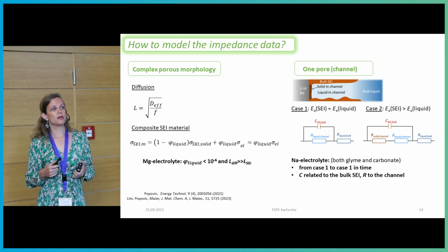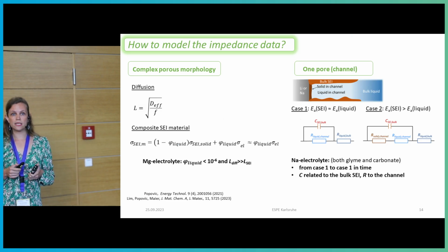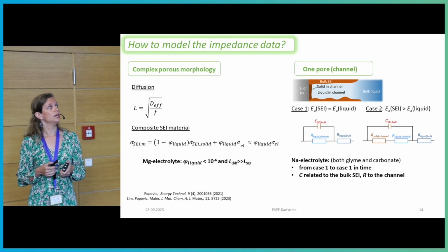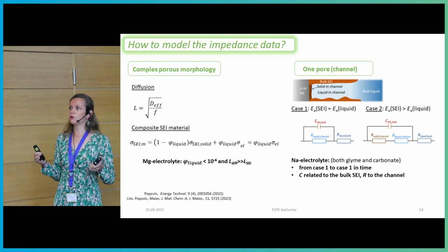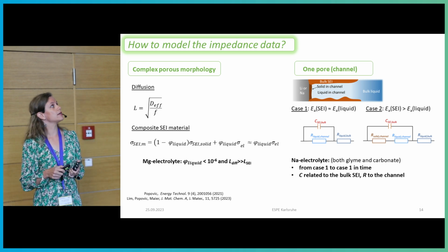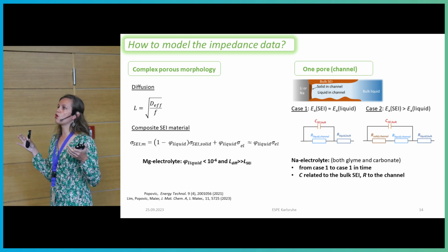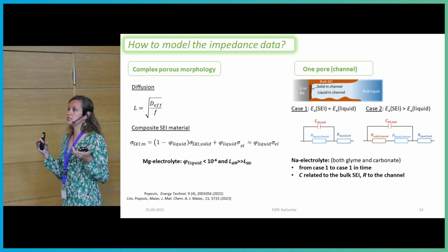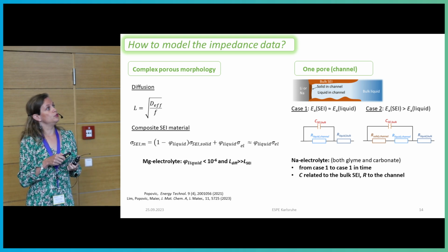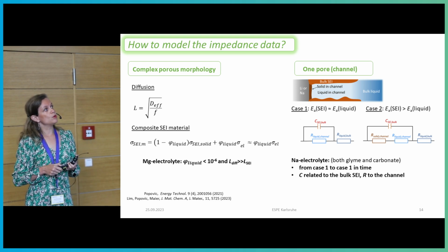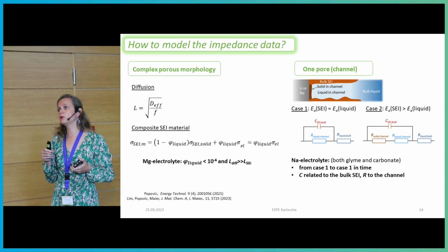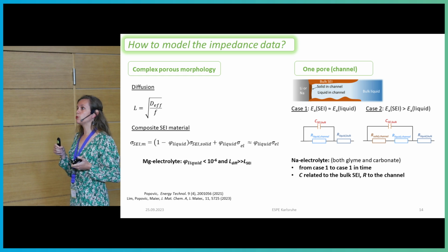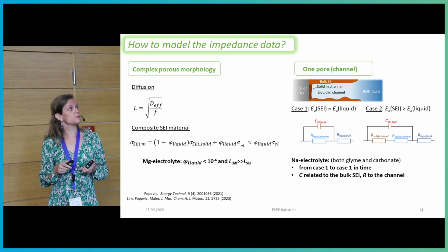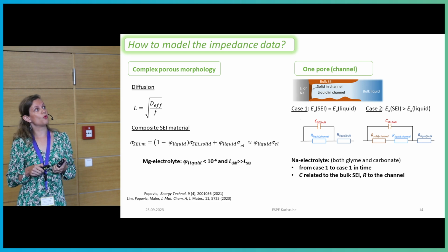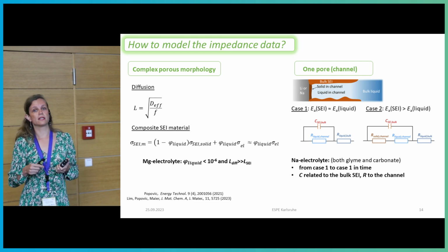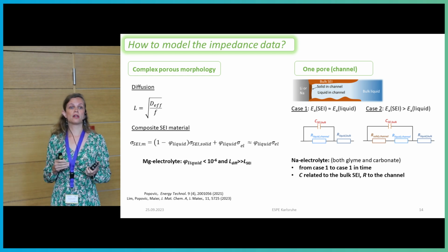So for me, the most important part was how to actually model the impedance data, because this is something that we collect quite a lot. And I can suggest two general ways of approaching these impedance data. One is taking into account the full complex porosity of these SEIs and trying to model the diffusion. In that case, for example, for magnesium, we can see that we need a very tiny amount of liquid in order to have dominant liquid pathways in the SEI in terms of transport. Or we can try to model one pore or channel with these kind of equivalent circuits and then say that we have many of these channels in parallel.